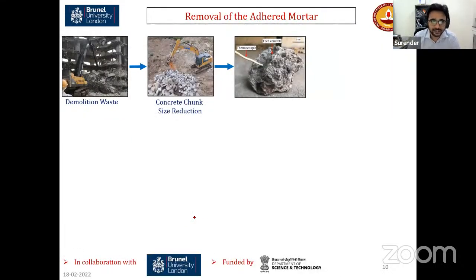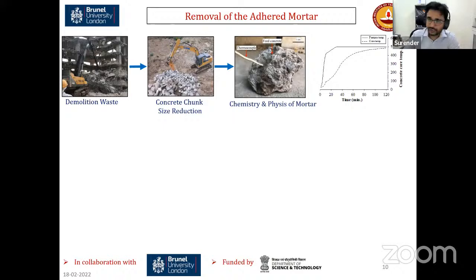Then, as Rohit already mentioned, we are working from crushing mechanism to strengthening the adhered mortar to removal of the adhered mortar, right? Normally, if we know the physics and chemistry of the adhered mortar, it has different hydrated compounds. So if you heat it for a certain duration, let's say at around 450 to 500 degrees centigrade for around 1 hour, the dehydration could happen, right? But for that you need a lot of energy. You need to keep it in the oven, microwave, or furnace, which is again energy intensive, right?